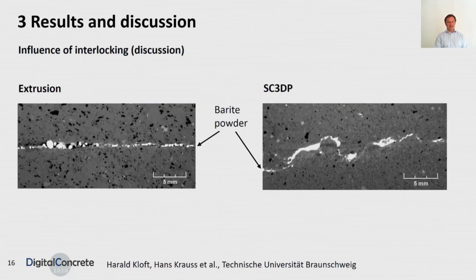Now I'd like to come to the second main influencing factor, namely the influence of mechanical interlocking exhibited by microscopic roughness of the interface between two layers. In order to investigate this, we performed extra tests with the same printing methods and the same process parameters, where we strewed barite powder on the substrate layer in order to get a better contrast later on in the computer tomography. And afterwards, we applied the second layer. Now, here you can see the results from computer tomography. On the left side, you see the layer or the interface.